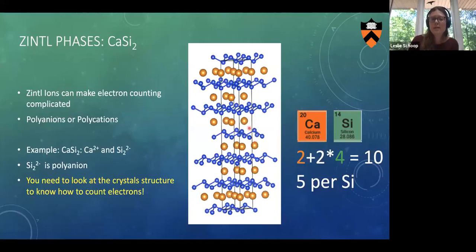If you look at the crystal structure here, you see that each silicon forms three bonds to other silicons. That means that, similar to a nitrogen atom, where you might know the molecule ammonia, when nitrogen forms three bonds to hydrogen, this silicon also saturates its electrons by sharing electrons through bonds, just like molecules do. And so this is an example of a polyanion, which is very common in solid structures, and how you can have a semiconductor while having a formally non-charge-balanced electron system. So it really gives us a lesson that we have to look at the crystal structure to be able to count the electrons. You cannot just blindly do it by looking at a formula sum.